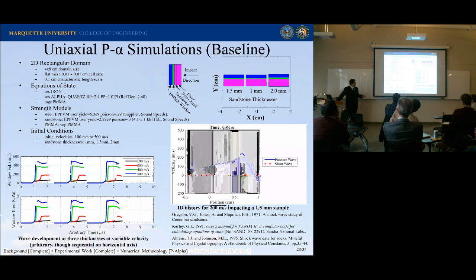Here I've done a number of different simulations. If you recall from before, I'm going to do a callback. If we look at this one right down here at 100 meters a second, you can see it's got one wave, and it's really slow velocity. But if we look at this higher velocity one, at 200 meters a second, we can see that we've gone above the plastic regime because we've got two waves. We've got this small one and then a bigger one, right? And then you can see that slowly starting to taper off in this 400 meters a second one. And by 500 meters a second, we've overdriven our sample. So you can see that from before on our different slides.